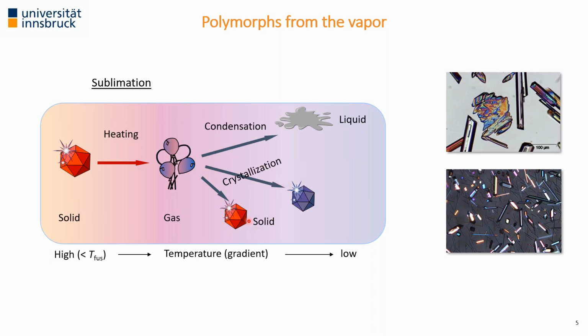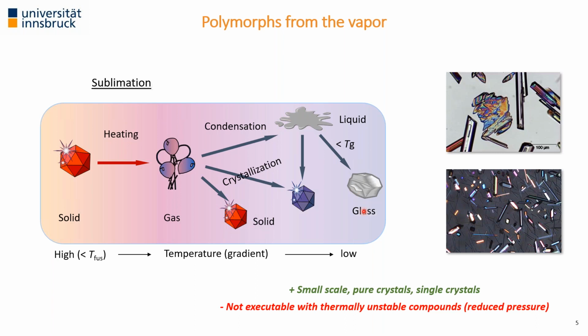What very often happens as a byproduct of the vapor deposition is condensation. We have liquid droplets, but sometimes they nucleate and we again get crystals, or if you are below the glass transition temperature, we end up with the amorphous phase. So you can see that by varying the conditions, there is a possibility to get different polymorphic forms, crystalline states, or sometimes, when we go through the condensation process, a glass state. Just once more: sublimation works very often, and the big advantages are that it's at a small scale, we only need a few crystals, and we end up with chemically and physically pure crystals. If you take one crystal of this, and very often we get single crystals, we can then proceed to further experimentation.